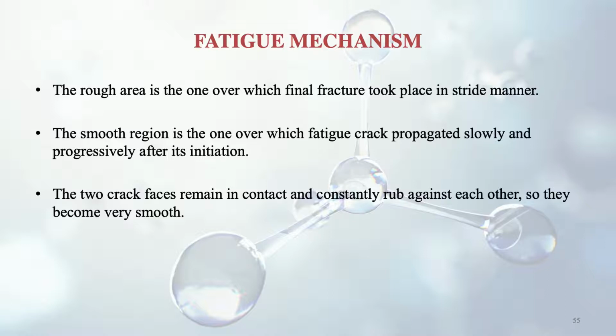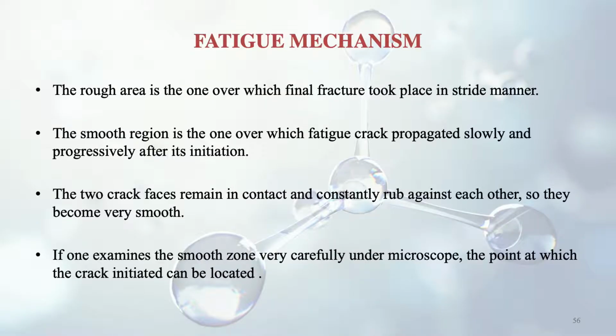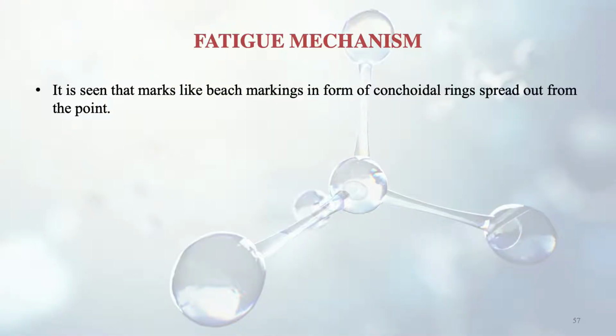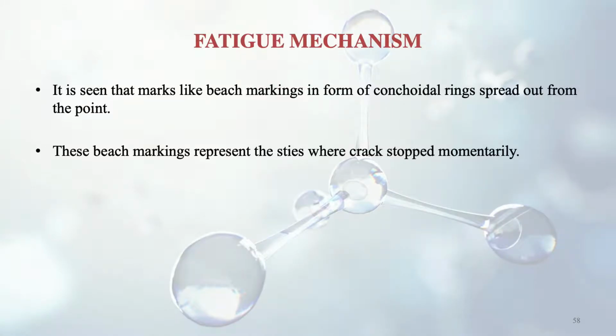So the rough and the smooth one are both in contact with each other, and they constantly rub against each other, so they become very smooth. These two surfaces are rubbing against each other, causing a smooth surface to come up. If one examines the smooth zone very carefully under a microscope, the point at which the crack initiated can be located. So from the smooth zone, if we look under a microscope, we can find the point from which this crack has initiated. It is seen that marks like beach markings, in the form of conchoidal rings, spread out from the point. So there are some rings. You know a ring is a somewhat concentric circle, so that type of rings come up. These beach markings represent the sites where the crack stopped momentarily.